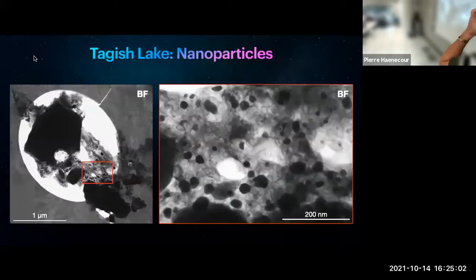If you look in more detail at the nanoparticles, you can see that while a lot of them show this more circular texture, some of them clearly have a more irregular shape, showing that they are probably crystalline metals. So you actually form metal particles, not just iron nanoparticles. And then if you look at the carbonaceous material, there is this curly shape feature that you can see around, basically reflecting this graphitization. So going from this diffuse aromatic carbon into more organized sheets of graphene, so graphitic layers.